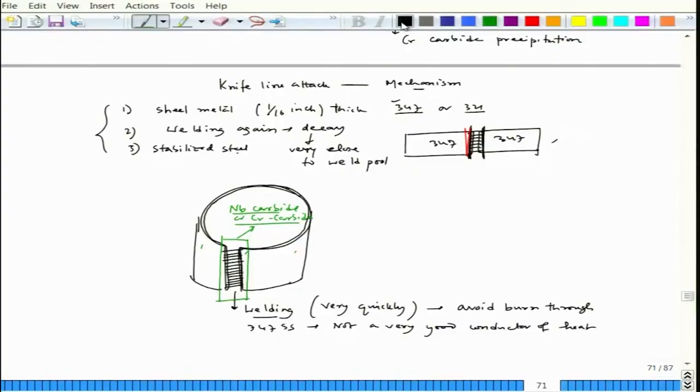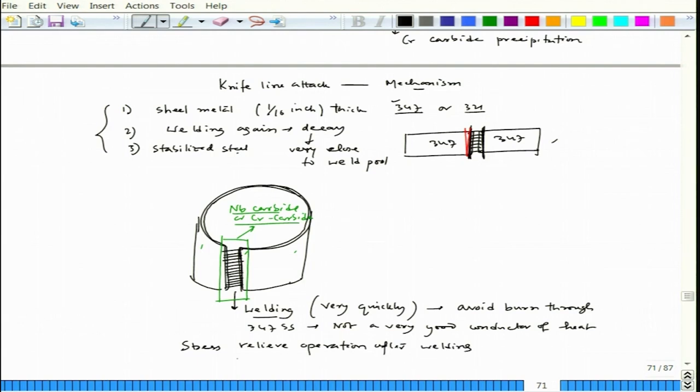The problem happens during stress relief operation. Because it is a thin sheet, there could be significant built-in stress due to quick cooling after heating to very high temperatures, and there is a possibility of warpage — thin sheet welding always leads to some warpage. There is a lot of thermal strain near the weld zone, so a stress relief operation after welding creates the problem.